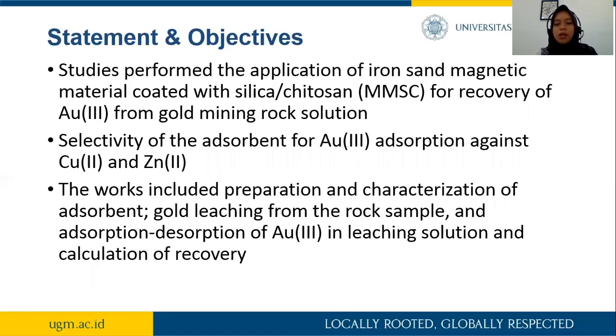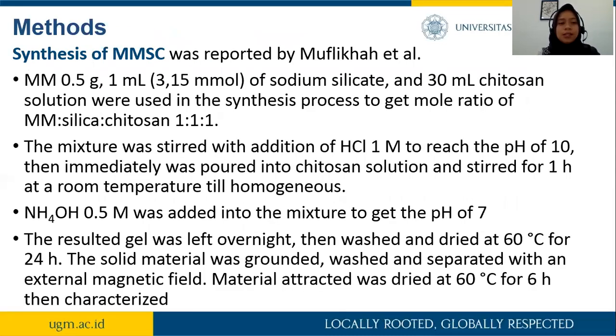Our objective, the work includes preparation and characterization of the adsorbent, then gold leaching from the rock sample, and the last is adsorption and desorption of Au3+ in the leaching solution and calculation of recovery. The method, the first, synthesis of our adsorbent. There is the mixture in the synthesis process to get a mole ratio of magnetic silica chitosan 1:1:1. The mixture was stirred with addition of hydrochloric acid 1 molar to reach the pH of 10, and then ammonium hydroxide 0.5 molar was added into the mixture to get the pH of 7.